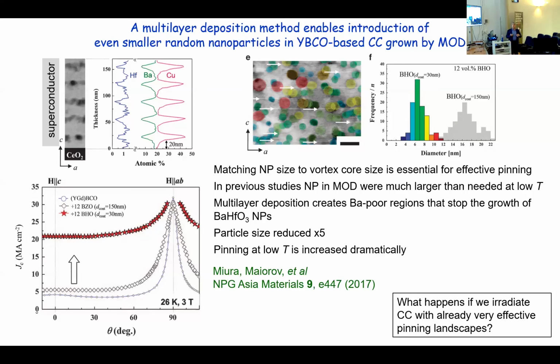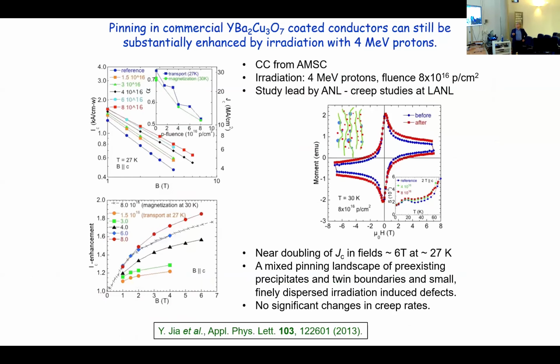Now, what happens if we take one of these very high JC coated conductors and we irradiate them? Well, this is work that we did with the people at Argonne National Lab. We took some MOD samples, coated conductors from American Superconductors. We irradiated with 4 MeV protons, and we observed, similar to the protons that I used many years before with the single crystals, systematic increases of the critical current density with fluence. You can see here the fluence dependence at different temperatures as a function of magnetic field, and it keeps growing with higher field.